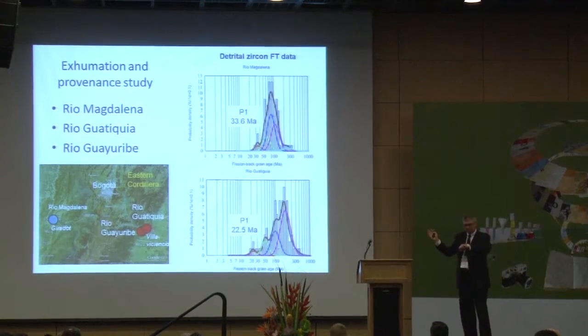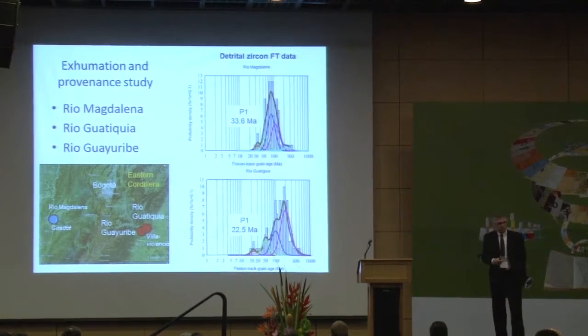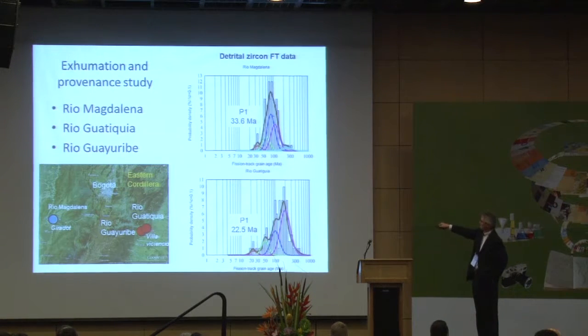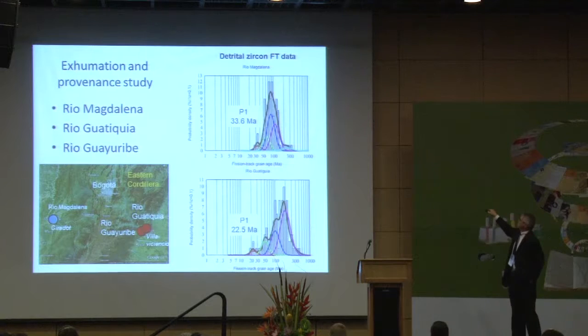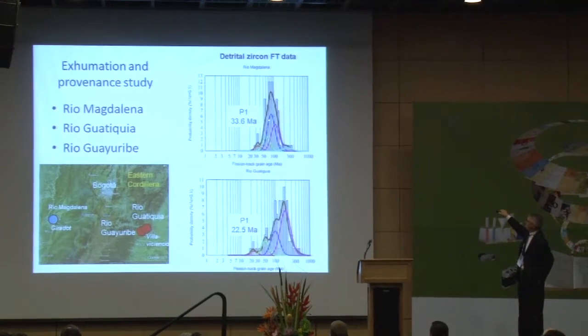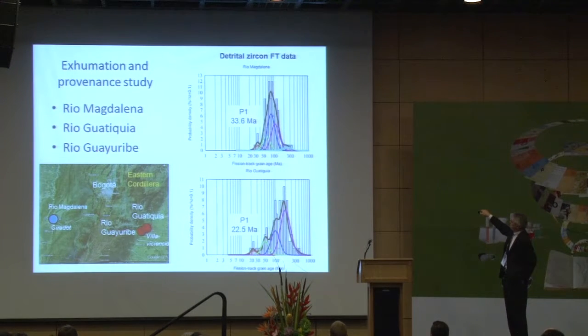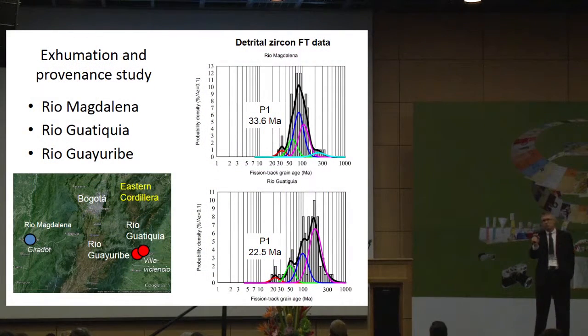If you now look at the zircon fission track data in these samples, we get a different picture. Now, this is the fission track data. We analyzed about 100 grains for this, and you can see we can distinguish statistically different age peaks or age groups, the main grain age populations in these samples.